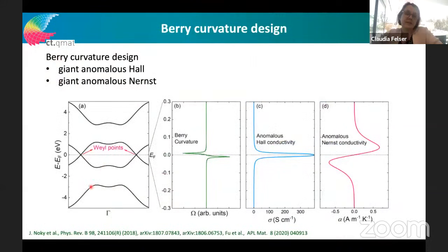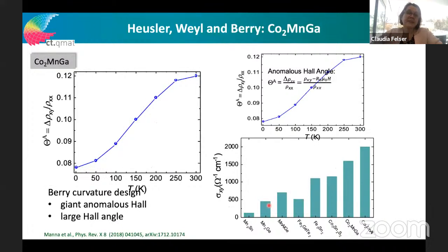So then recently in my team, we did some toy model calculation to really understand this. What are the contributions, which are fingerprints, also to find more materials which show giant anomalous Hall and giant anomalous Nernst effect. So we simply did it for the case of Weyl points, for example, and then you see that you get these peaks in the Berry curvature, which then leads to a peak in the anomalous Hall conductivity. And since the Nernst effect is the first derivative, we see also a giant response in the anomalous Nernst. And here's a measurement.